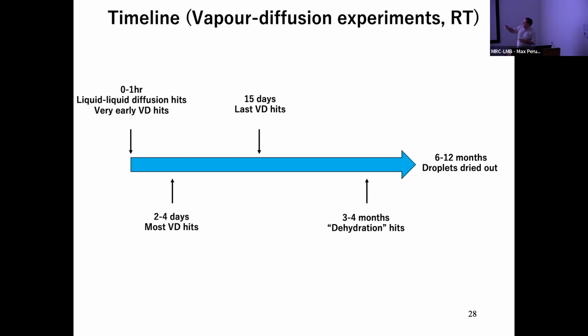After a few days, 2-4 days, most of the equilibrations between the drops and the reservoir are completed or almost completed. So at this stage, if you don't want to check your plates too many times, that's a good step. So let's say you wait 4 days, and then you have a first result that gives you a good indication if it's going to work or not. Then I would say after a couple of weeks, all the vapor diffusion experiments are completed. So it's another good timing to check.